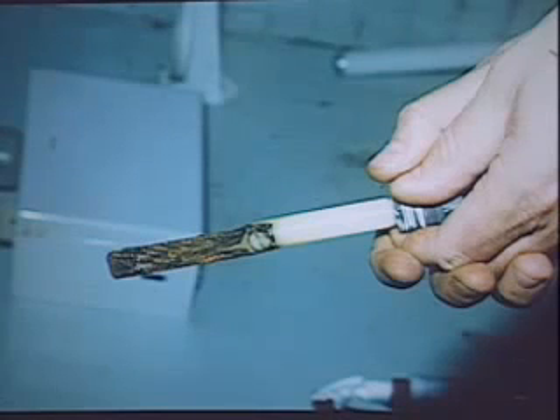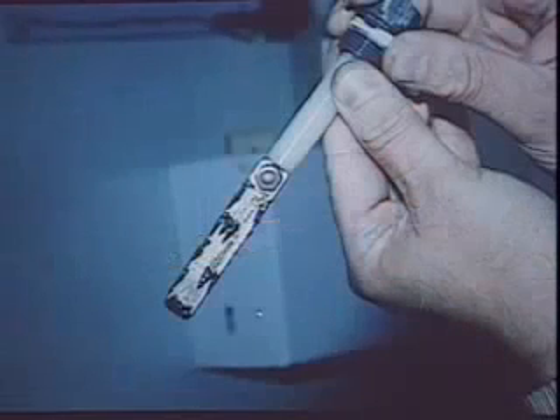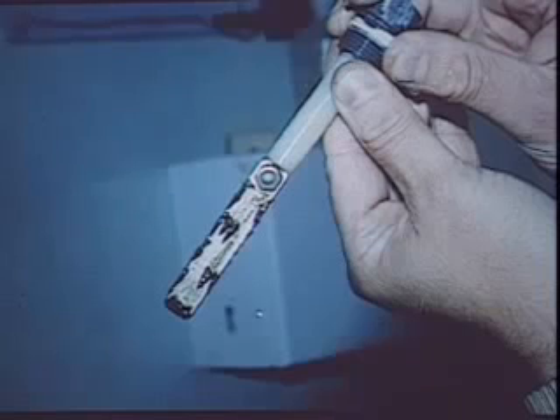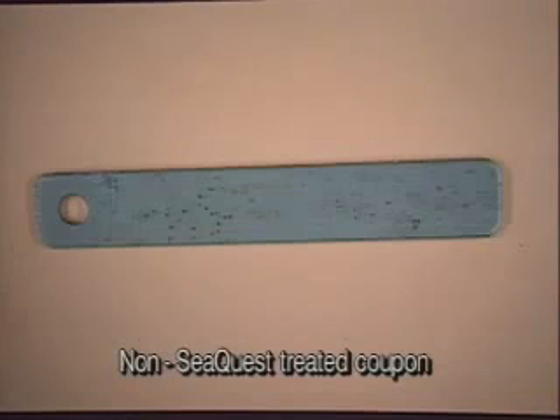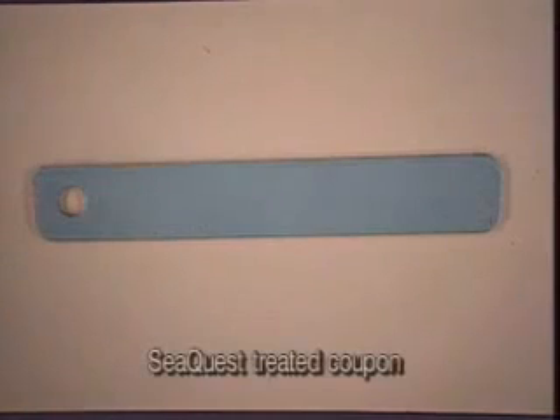As you can clearly see from the first coupon, which came from the non-Seaquest treated side, the entire coupon is covered with heavy tuberculation. We then look at the Seaquest treated coupon to see that there is barely any tuberculation on the coupon. We then send the coupons out to Metal Samples for them to be cleaned and weighed. As we can clearly see, the non-Seaquest treated coupon is heavily pitted, and the Seaquest treated coupon is totally devoid of any pitting. This shows the strong corrosion control, pitting control that Seaquest has, once again, saving your system the loss of pipes due to pitting.